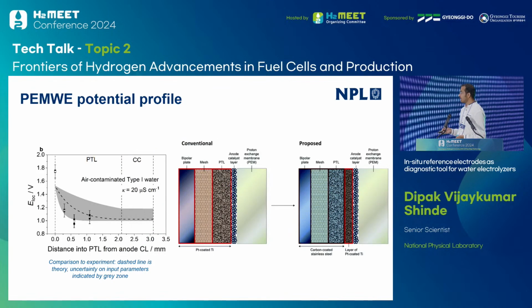And our measurements validated the model, which are shown here. So in air contaminated type 1 water, which is about 20 microsiemens per centimeter, you can see that the voltage drops immediately after the anode layer. So within like 150 micrometers, the voltage is already non-corrosive for the components.